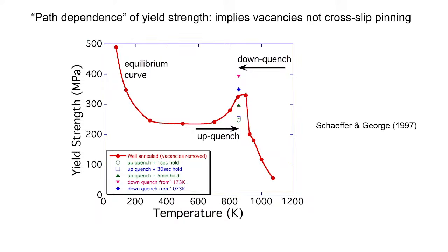So, if you approach it from the high temperature side, you've already quenched in the high vacancy concentration that has been set at the high temperature. But if you were able to rapidly heat from room temperature up to this, then maybe if the heating rate is fast enough, you maintain the low vacancy concentration. And that's indeed what we saw.